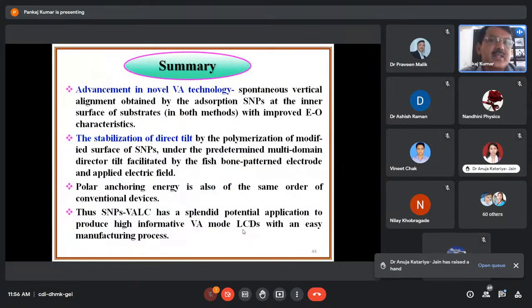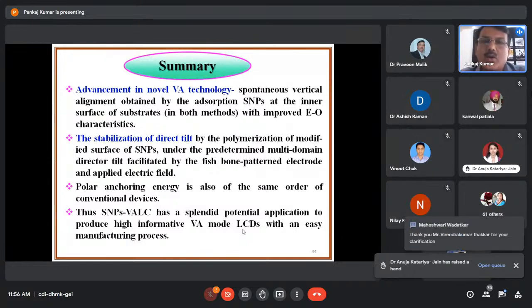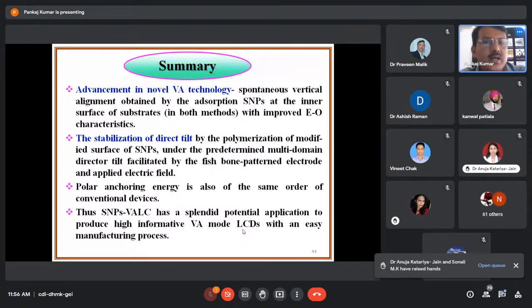So if I summarize this work: the advancement in novel VA technology, the spontaneous vertical alignment obtained by the adsorption of silicon nanoparticles at the inner surface of substrates in both methods with improved electro-optic characteristics, the stabilization of the director tilt by the polymerization of the modified surface of silicon nanoparticles under the predetermined multi-domain director tilt facilitated by the fishbone pattern electrode and applied electric field. Polar anchoring energy is also of the same order as conventional devices. Thus, SNPs-VALC has splendid potential application to produce high informative VA mode LCDs with an easy manufacturing process.